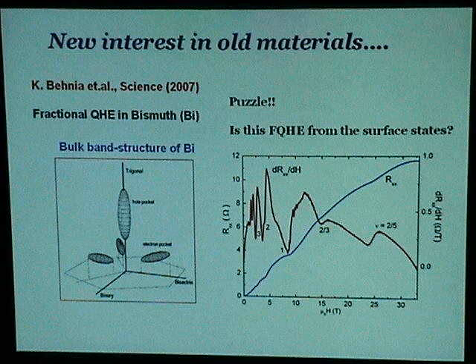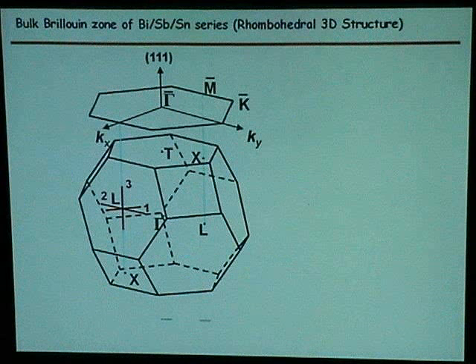Now, if I look at the reciprocal space, it has a rhombohedral 3D structure, and one can see it has many faces. So this is the 111. It has many other faces. So in order to confirm that the fractional quantum Hall effect observed in bismuth has to do with a surface state, I have to look at all the surface states and get the electron density and all that and correlate it to the field where these Landau levels are observed. I mean, these fractional levels are observed.